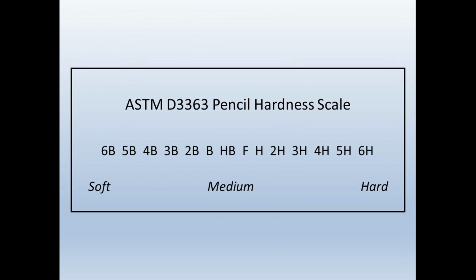But it's basically different hardnesses of lead, and you attempt to gouge the lead into the lining system. If it does gouge, it's not ready. If it doesn't gouge and the lead actually gives way, it means the lining is cured. Okay? But again, the manufacturer's going to have to give you that pencil number. They might say, you want to achieve a 3H, you want to achieve a 4H hardness before it's ready to go. And you can test that way.